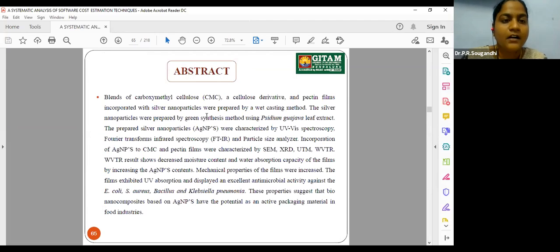So, coming to the abstract, this is the preparation of bio-nanocomposite films. The bio-nanocomposite film is a blend of two polymers, CMC, which is carboxymethyl cellulose, a cellulose derivative, and pectin. The combination of these two polymers incorporated with silver nanoparticles makes the bio-nanocomposite films, which are prepared by the wet casting method. The silver nanoparticles are prepared using guava leaf extract, which is a green synthesis and an eco-friendly method.